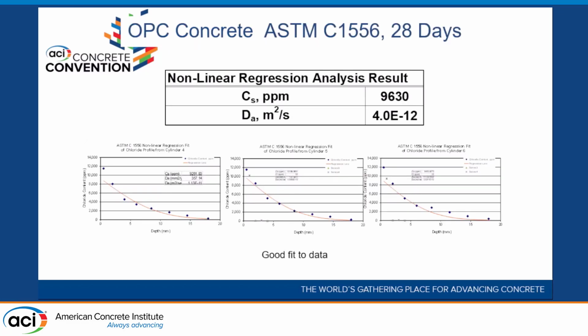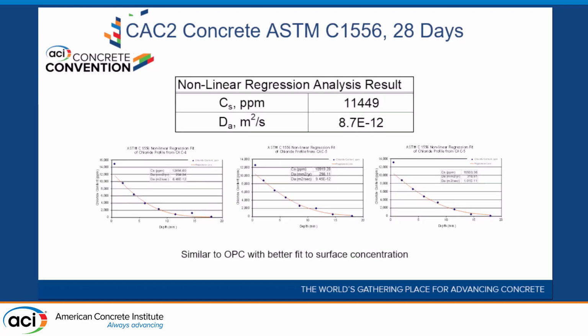Looking at the controls, now this is ASTM C1556, the standard method. You ponded them for 28 days. We also did longer times, which I'll show you. For the control, the OPC, nice diffusion curves, with a value of about 4 times 10 to the minus 12 meters squared per second. We have a CAC2, which also did extremely well on this, a little bit higher than the control, but once again, very nice curves.